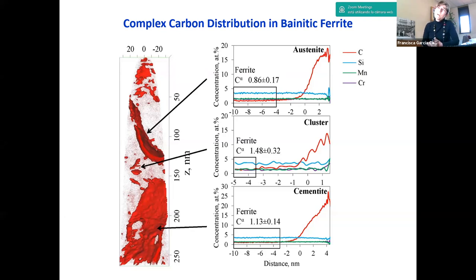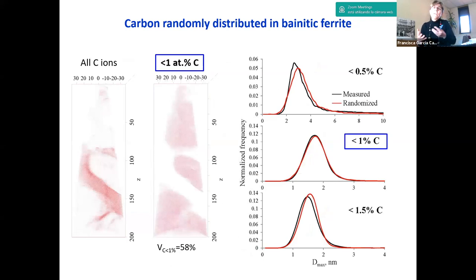The question is not how much carbon there is on the other side of the boundary in austenite or in cementite. The question should be how much carbon there is in this sample randomly distributed. To do that, we need to do a certain data mining exercise. What we did is remove any carbon enriched regions, and to do that, we determine a threshold of carbon content below which should be the bainitic ferrite matrix, and above which should be any carbon enriched region. But the threshold should be determined ensuring a random distribution of the carbon in the matrix. That's what we did. You can see here an example.